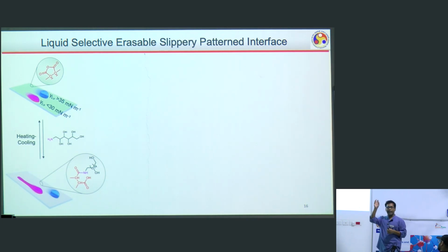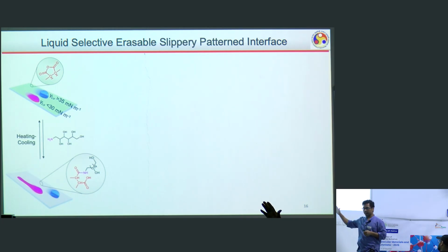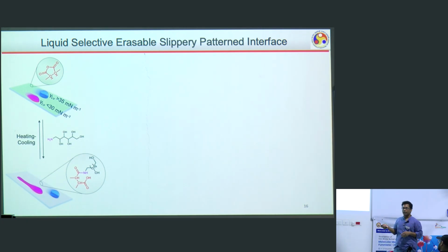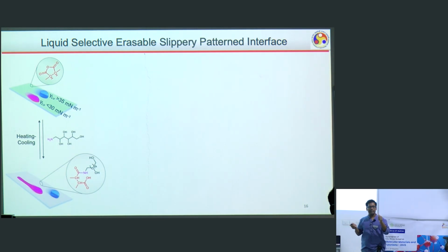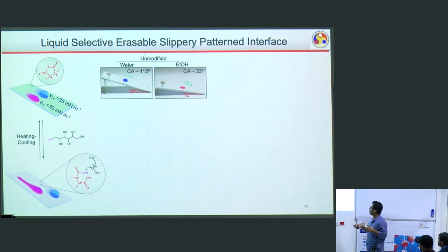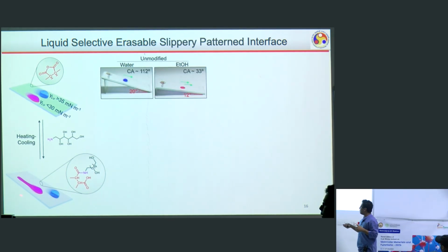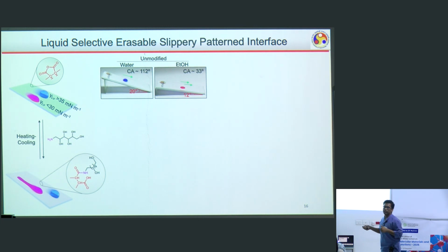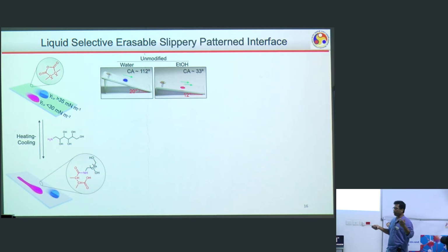Okay, what about the maleic anhydride, is it available only on the surface? Because this is a smooth interface, right? Only on the surface do they undergo this chemical reaction and install this hydrophilic domain, precisely changing the surface free energy. Because of that, what happens? It selectively compromises the slippery property against low surface tension liquid, but high surface tension liquid, that is water or similar, can easily keep on sliding off. Okay, this is the data you can see.